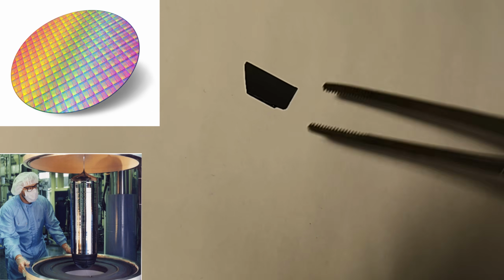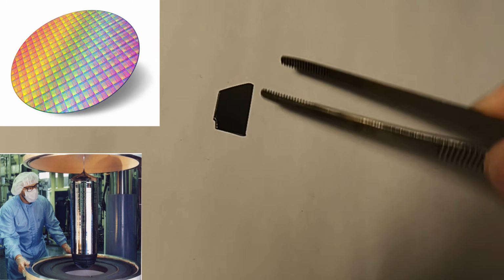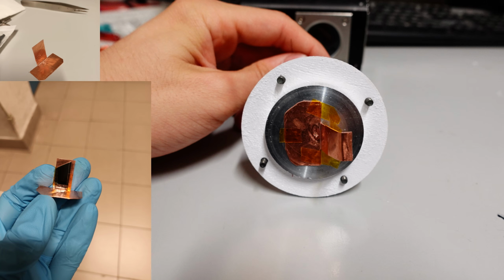Since we need a very shallow angle, I placed the silicon chip on this copper support that is almost parallel to the incoming electron beam, and made a pinhole in the copper so that only a very thin beam of electrons could pass through the hole and hit the crystal of silicon. It required quite a few attempts to get the right position and angles, but I finally could see some strange reflections that weren't in the same position as the main transmitted beam.